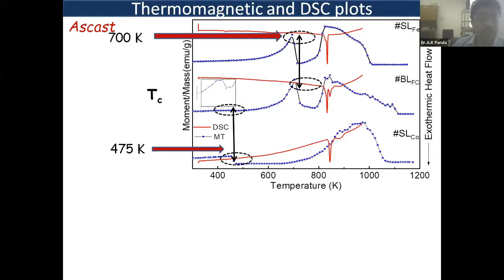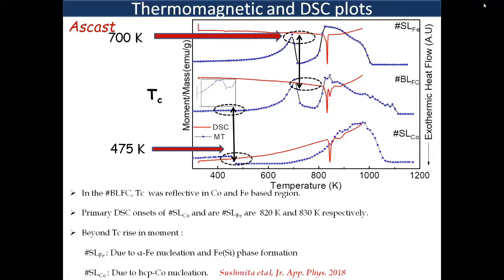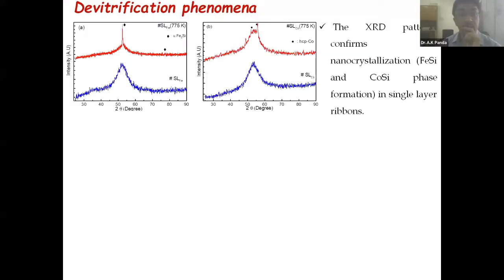So these are the two temperatures which are important to look into. These are the low temperature transformations, magnetic transition temperatures. Of course, it is much lower than the crystallization temperatures. So I move to the next one. These ribbons look like this. In the X-ray diffraction, it is amorphous, and when you crystallize it, they form iron silicides and so on.